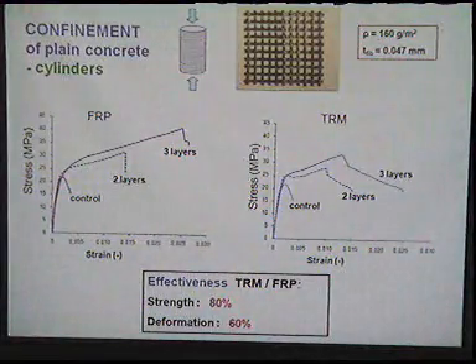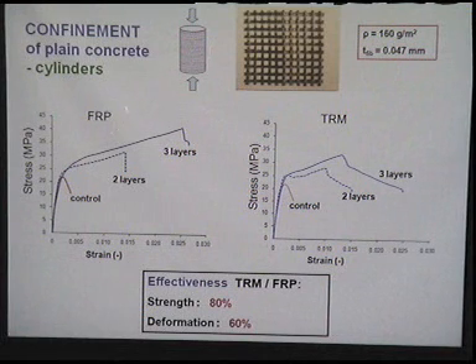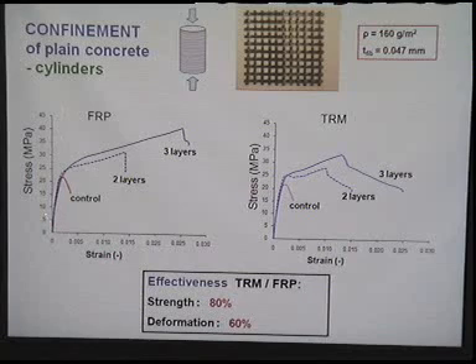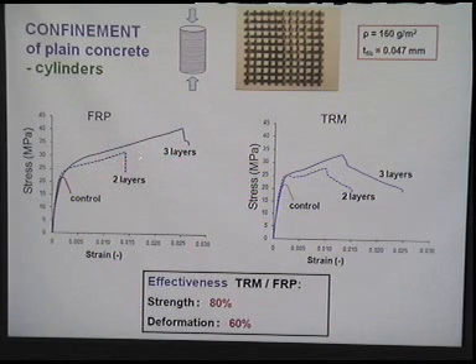So we wrapped concrete cylinders with FRP and then with TRM, and we looked at typical stress-strain plots. Red curves here show the response of unconfined concrete, and blue shows the response of concrete confined with FRP here and with TRM there. We see that TRM is not as good as the FRP in this particular case in terms of strength and deformation capacity. But if we compare it with the control specimen, that is the one without confinement, it is quite good actually. We have an increase in the strength, and we have a dramatic increase in the deformation capacity.